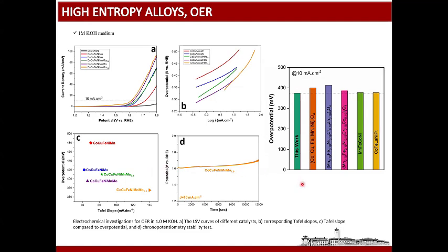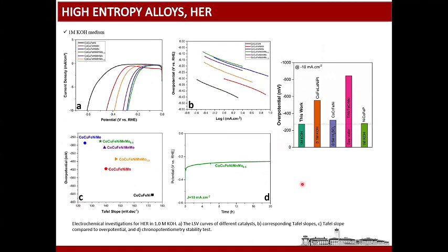It is stable and it works for oxygen evolution reaction. And we also tried hydrogen evolution reaction, and in this case the molybdenum 0.5 composition produced the lowest overpotential, and also it's quite stable. And then again, overpotential decreases a little bit, but over 20 hours it is quite stable.